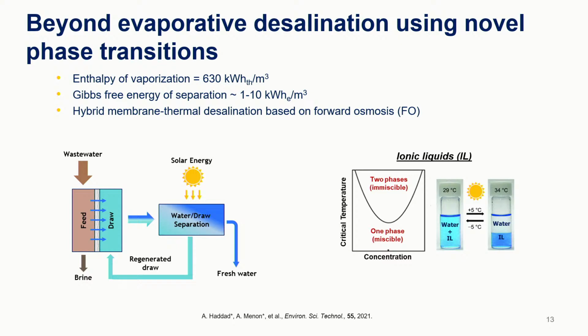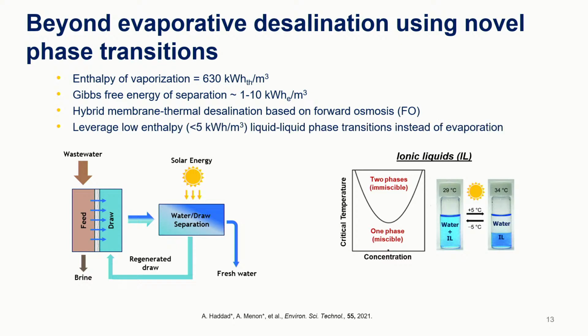So what that means is at room temperature, the ionic liquid and water across all concentrations form a single phase mixture. But as we start heating up, we hit this two-phase boundary, and then at a certain critical temperature, our ionic liquid and water are now immiscible. And so because of density differences, the ionic liquid settles at the bottom while the water layer floats on top. So this is also a thermal separation, but it's purely a liquid-liquid phase transition rather than the liquid-vapor phase transitions we were talking about. And the biggest advantage in this case is that you can have much lower enthalpies for these phase separations compared to the latent heat of vaporization.